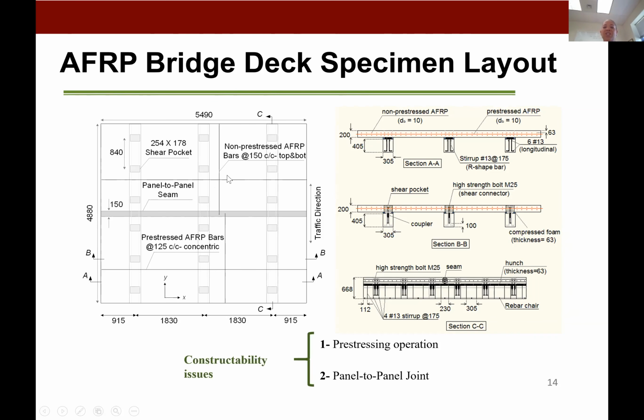So what we also did was an equivalent force approach in terms of trying to figure out how much AFRP we needed. We also had AFRP bars on the top and bottom layers, non-pre-stressed, at about 150 millimeters center to center. In cross section, you can see we did have steel high strength couplers and threaded rods in the shear pocket to achieve that composite action between the deck and the girders. But you see the concentric pre-stressing strand along the section, and then top and bottom the non-pre-stressed AFRP bars. And the total bridge deck was 8 inches thick.